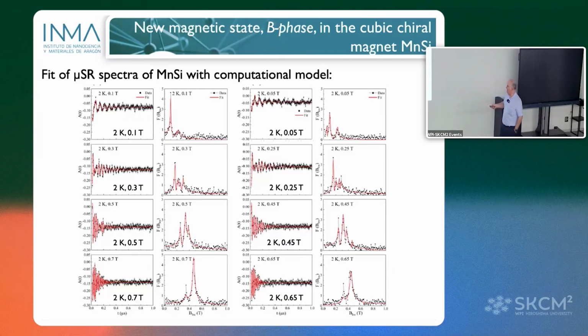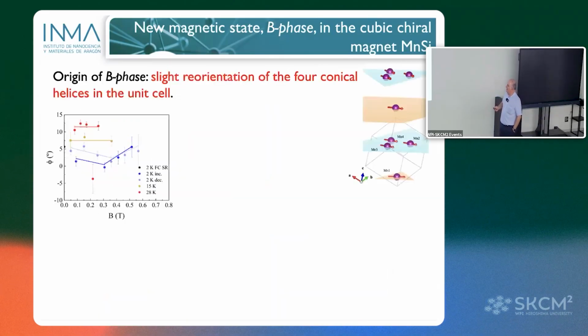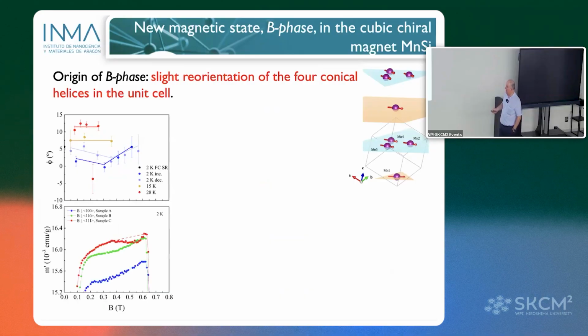We were able to fit more or less, and the results are here for different temperatures, but at low temperature, we observed a kind of trend that this phi angle seems to increase a little bit in the area where we observe the anomaly.